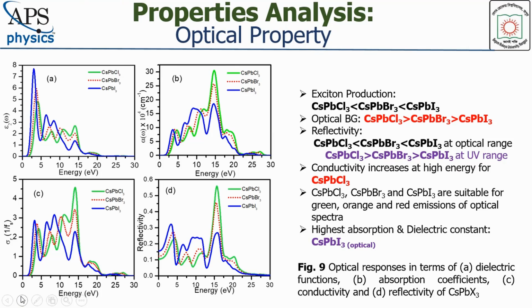Optical responses in terms of dielectric functions, absorption coefficient, conductivity and reflectivity of cesium lead halide has been shown in figure 9. Due to the higher band gap value, the exciton production is less for cesium lead chloride and it increases for bromide and iodide replacement. The order of optical band gap of these three perovskites are reconfirmed by absorption spectra. It is highest for cesium lead chloride and the lowest for cesium lead iodide.